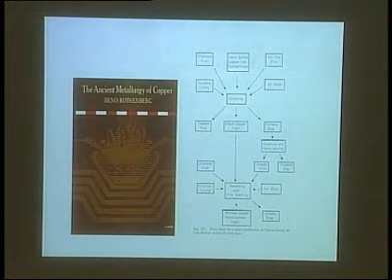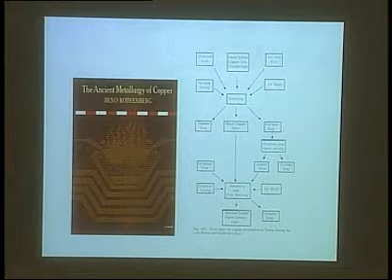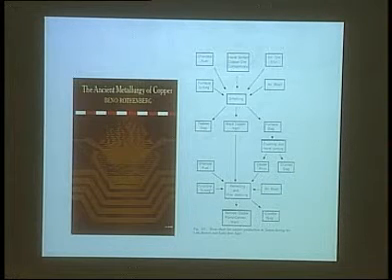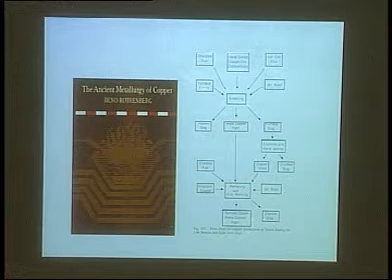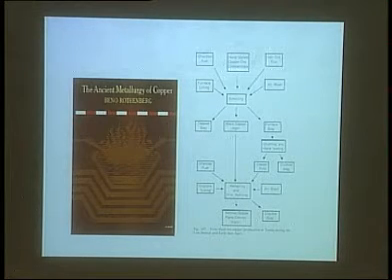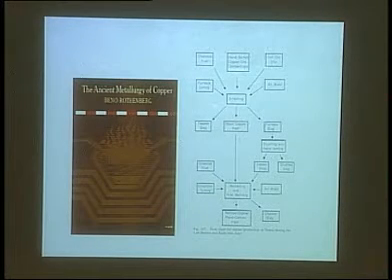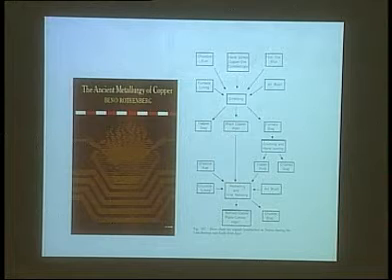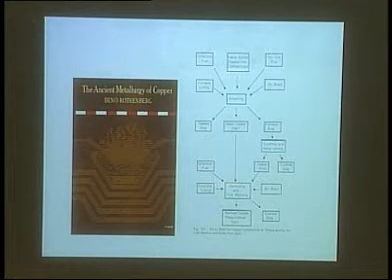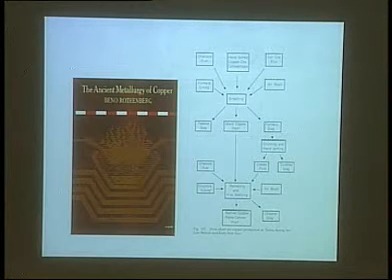So here's the smelting up at the top. In terms of important inputs, we've got high-grade copper ore, we've got iron ore, we've got the air blast, we've also got the charcoal ash that we have to accommodate, and we also have poor quality furnace linings. Okay? That material, all added and smelting, produced an intermediate black copper, iron-rich ingot that we had to refine, and then refining, we produced more slag and a plano-convex ingot. Okay? So let's look at this question of plano-convex ingots quickly before we move on.